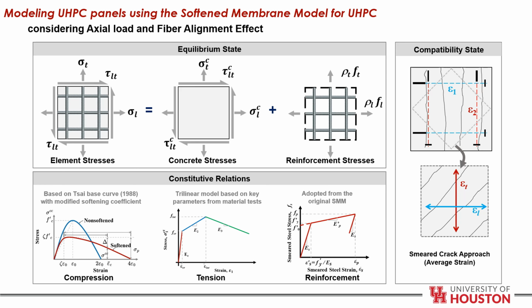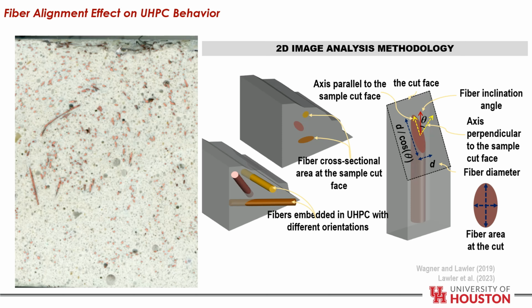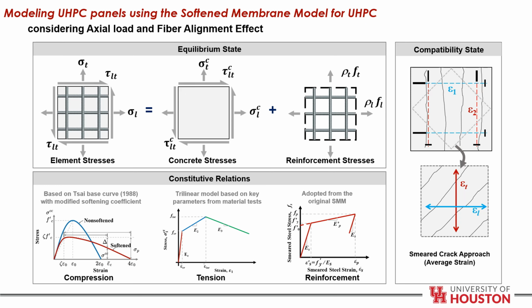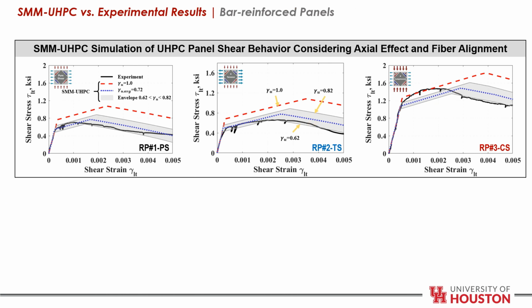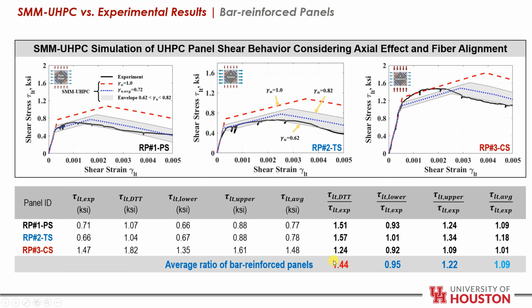The fiber alignment study resulted in a fiber alignment factor that was adopted in the softened membrane model, which is an analytical model that is used to simulate the shear behavior of UHPC panels, which consists of the equilibrium equations and the compatibility equations and the constitutive relations that were modified to suit the UHPC behavior. So the fiber alignment factor was applied to the tensile constitutive law of UHPC, and the results showed enhancement of the shear modeling response of UHPC when the fiber alignment factor is adopted. As we can see, ignoring the fiber alignment factor resulted in 44% overestimation of the peak shear strength.